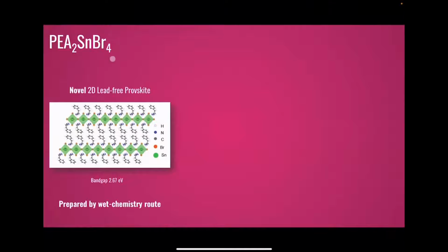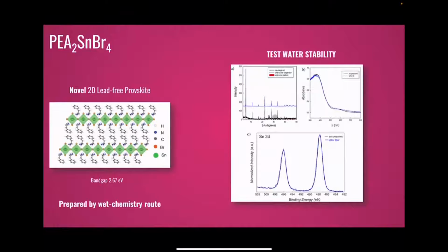This was a new perovskite, never prepared in the literature. We prepared it by wet chemistry, and immediately we tested the water stability. Perfect water stability, diffraction pattern after and before dispersion in water. Again, also this perovskite does not dissolve, but it is dispersed in water. You can see the particles of the perovskite. Optical properties are good as prepared and after water treatment, and also the XPS of tin is fine, and it is again tin 2+.